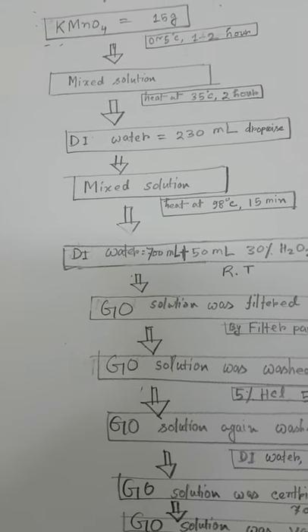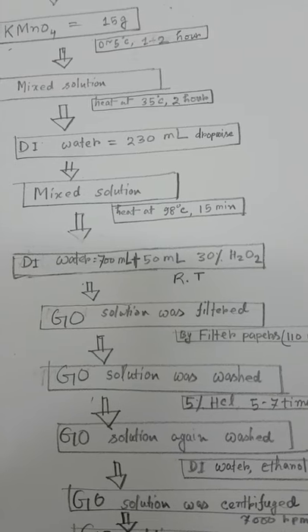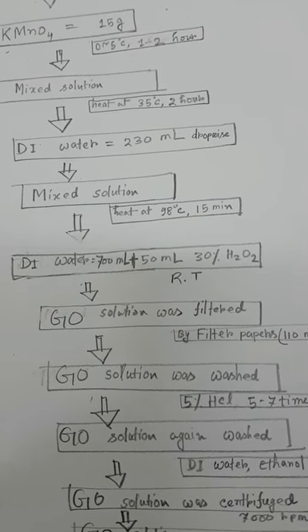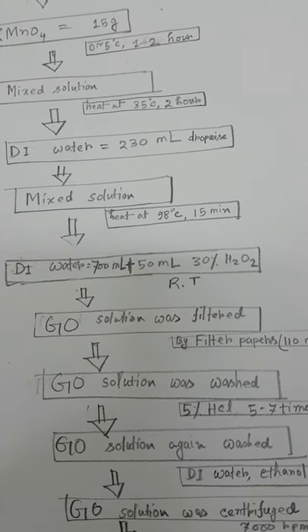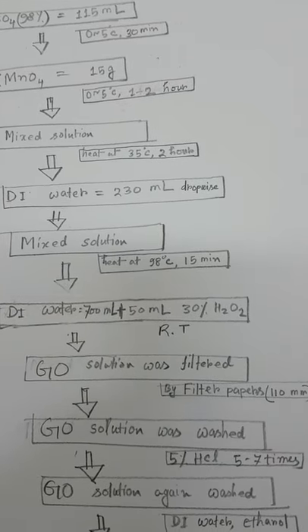I terminated the reaction by adding 700 ml of DI water and 50 ml of 30% hydrogen peroxide. Then graphene oxide is synthesized.